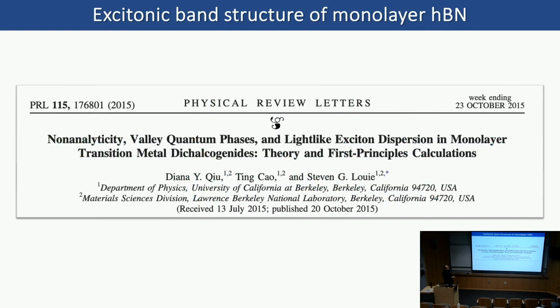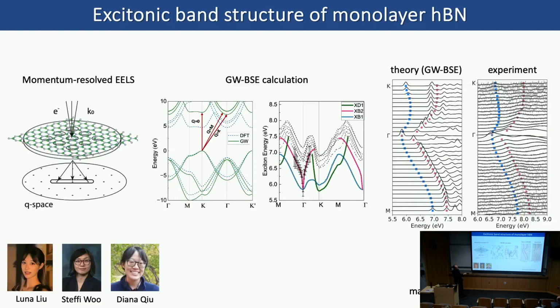So Diana did this almost 10 years ago, using GW calculation, to predict the light-like exciton dispersion in a TMD sample. But I believe nobody has ever observed it experimentally. So we were quite excited to confirm that in hBN, it also has this linear dispersion, and we could confirm experimentally that it does exist here. But the side note is hBN is an optically direct bandgap material with a dark mode that has a comparable energy with it. So that's our understanding of what a monolayer hBN should be like.